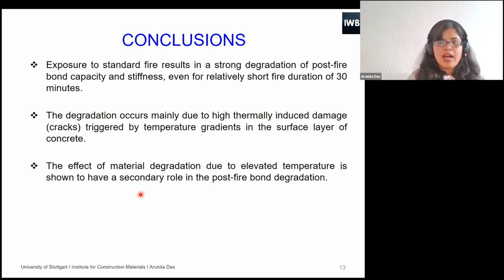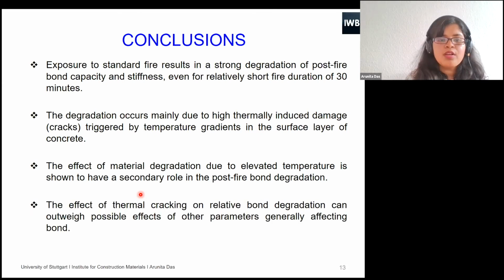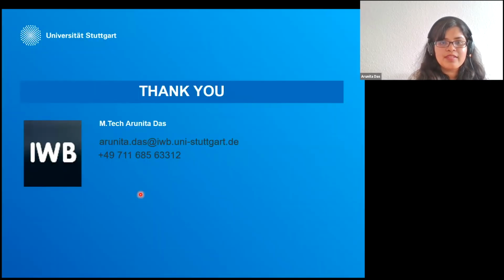In our case, we have considered an unconfined test setup, which simulates well the real behavior in the case of a beam or a slab. So the effect of thermal cracking on relative bond degradation can outweigh the parameters generally affecting the bond. So thank you so much.